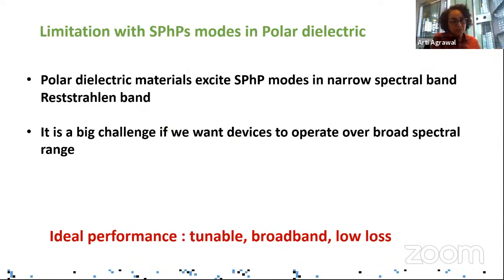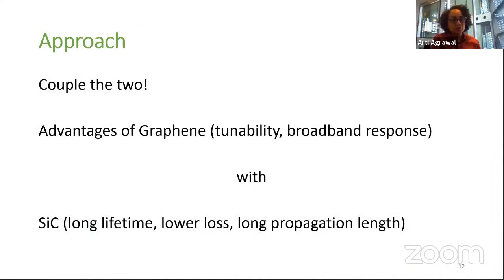But there are, of course, limitations with every material, including with polar dielectrics such as silicon carbide. The negative permittivity only exists in the Reststrahlen band, which is a narrow region. So if we want to go beyond the Reststrahlen band, that's not possible with these polar dielectric materials. And how do we want to then operate? Because the ideal performance that we want is tunability, broadband operation as well as low loss. So that would be the situation that we would have in the best possible world. So how do we deal with this?